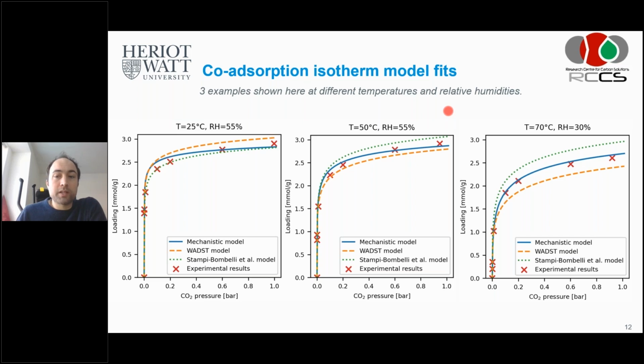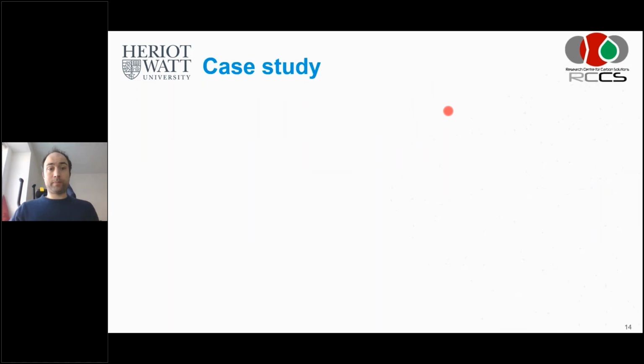You see it here for different temperatures and different relative humidities, and I think each model predicts better or worse at a different set point. We didn't find that one model always outperformed the other models, and they all have their regions where they are okay. But what we did see is that the mechanistic model, across the range of temperatures and relative humidities, is pretty accurate in predicting adsorption.